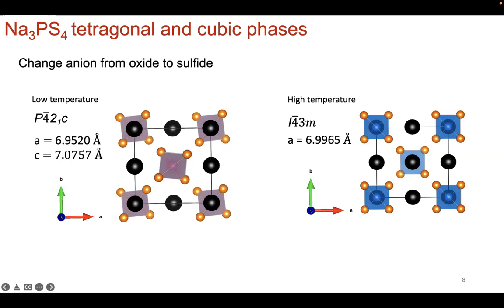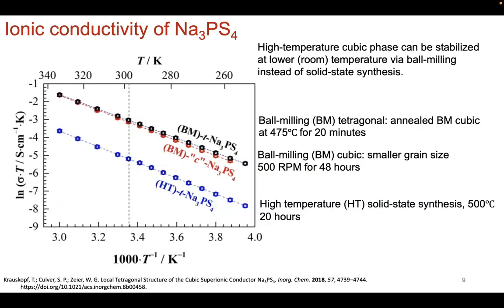Now at the high temperature phase, you have the cubic structure, this I4 bar 3M structure, and you can see the lattice parameter is quite similar. It's really close when it comes to tetragonal and cubic. So you can imagine that the change is not going to be that difficult. You're going from 6.95 to 6.99. So it's a very subtle change. But now you have the ordered tetrahedra that you see there in blue that you don't see, you see a little bit of the twisting in the tetragonal phase. Okay, so it's these subtle differences that result in large differences in the ionic conductivity at the end of the day. Okay, and so how do we tease that out? Well, we can do electrochemical measurements. Of course, we can also tie them in with materials characterization to really try to understand it.